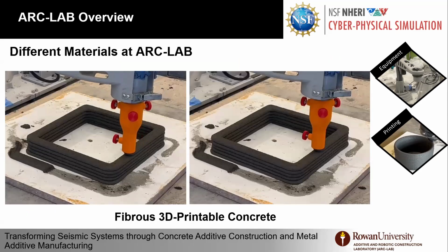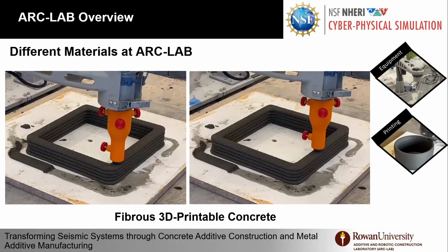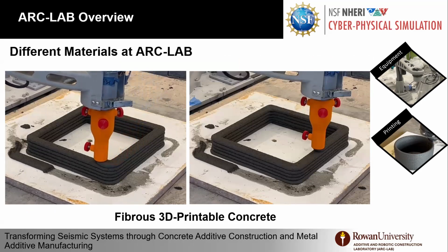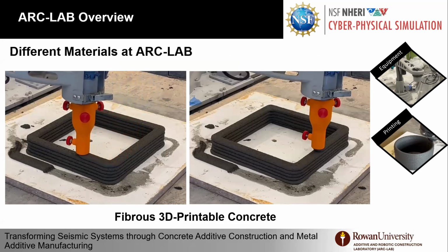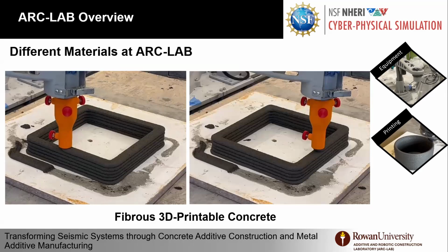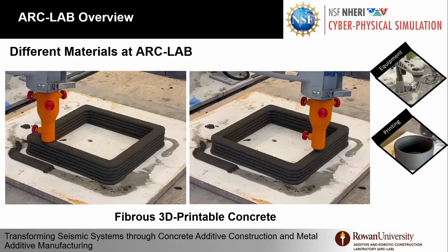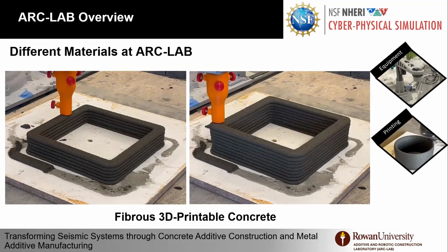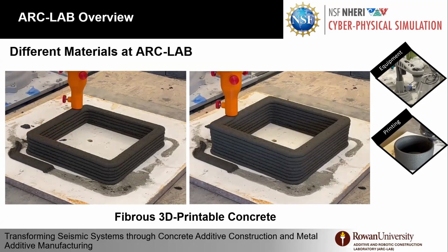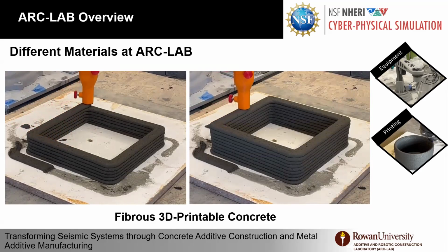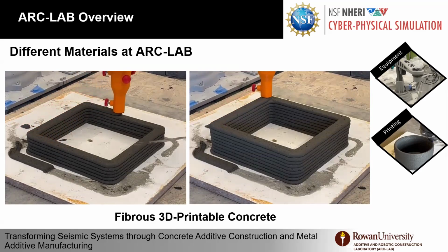We also develop materials. We realized that the material is brittle, as concrete always is, so we incorporate fibers into the material, steel fibers of different lengths. We were able to print with 4.5 millimeter, 6 millimeter, and up to 12.7 millimeter steel fibers. As you can see here, printing on the square, we use the square as a benchmark for cutting samples, testing cubes and flexure beams, and make it a standard for the quality of the print.